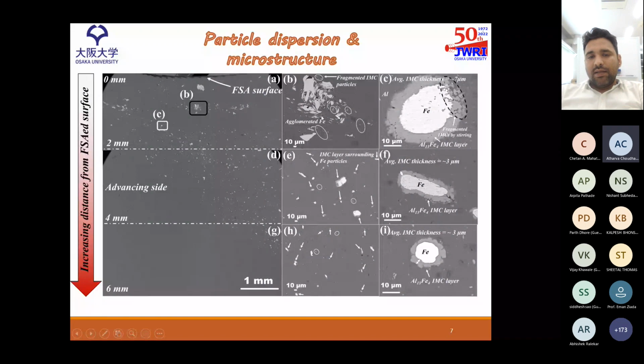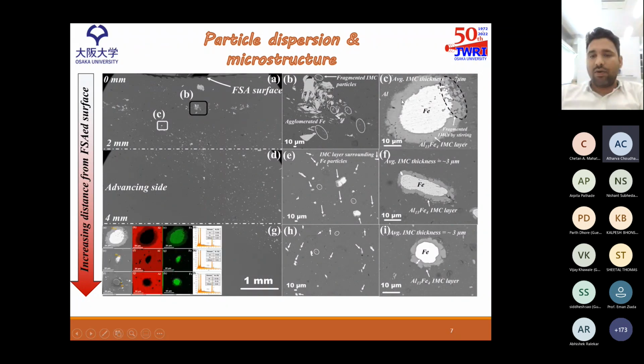Now the reason behind this is that in the top region, the shear stresses are higher, which leads to the fragmentation of this layered structure, and that's why this layer is not visualized. However, the fragmented particles of this IMC layer are visualized. This is the IMC layer which I'm talking about, and this is the Fe particle. And we have observed a variation in the color contrast. The black part is the aluminium, the gray one is the IMC layer, and the white bright one is the iron particles. So this is the reason for this distribution.